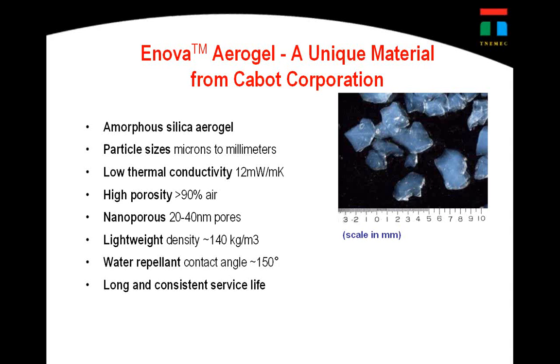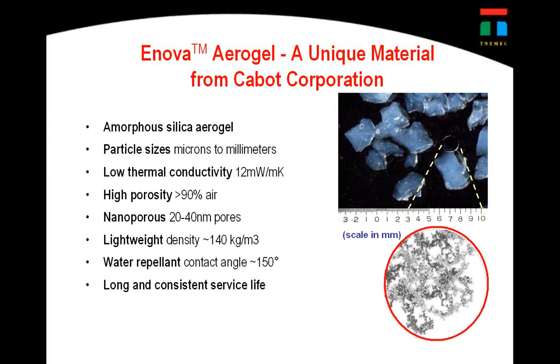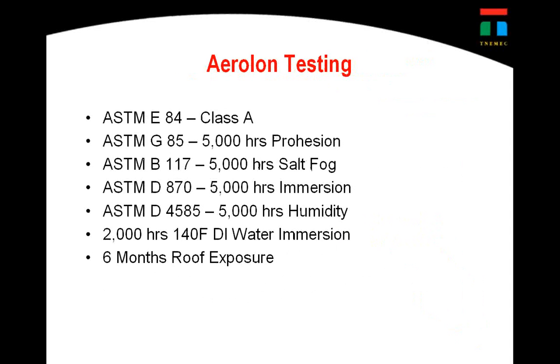And as we looked at it more closely, we realized that if we folded this particular silica into this resinous technology, we actually created the very first highly thermally insulative material at very low thicknesses. And why this was significant, because when you started looking at how this technology comes together, I'm just going to jump forward a little bit, and when we started playing around with different resins, we realized that not only do we have a material that was highly energy efficient and a very thin film, but was also extremely durable. And so we started running a bunch of tests.